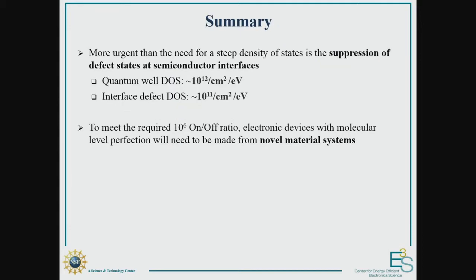But in summary, we think that the biggest problem facing TFETs is not just controlling the steepness, but getting the right on-off ratio. And what's preventing us from doing that right now is that there's a whole bunch of interface defect states inside the band gap, which is only about a factor of 10 or 100 smaller than the density of states in the conduction band. And that severely limits how well we can turn off our device. And since we're so far off from this 10 to the 6 on-off ratio, it seems to us that in order to fix this problem, we'll need to dramatically suppress these interface defects and possibly move to new material systems to accomplish that goal. And I'll just wrap up here. Thanks.